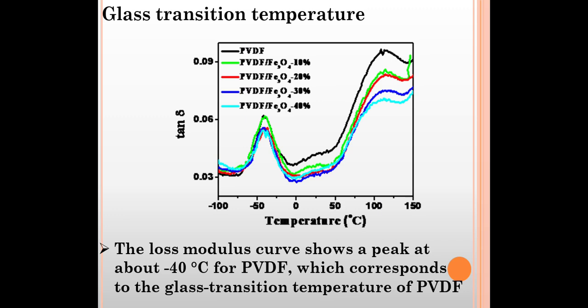The damping is studied with the tan delta curve as a function of temperature. This figure shows two peaks. One peak is appearing at -40 degrees Celsius. This is attributed to the glass transition temperature. The second peak at 120 degrees Celsius is attributed to the crystalline relaxation.